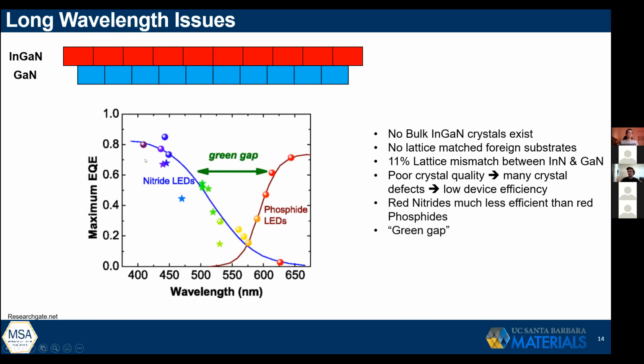And so as a result, nitrides are pretty efficient when they're blue because you need less indium. However, as you add more indium, this issue gets exacerbated, and so efficiency drops off. And then phosphides, which are only able to emit red light, or the band gap corresponds to red. I won't really get into that, but basically the efficiency drops off when you get to green for all material systems. And so there's this thing called the green gap that research is trying to address.